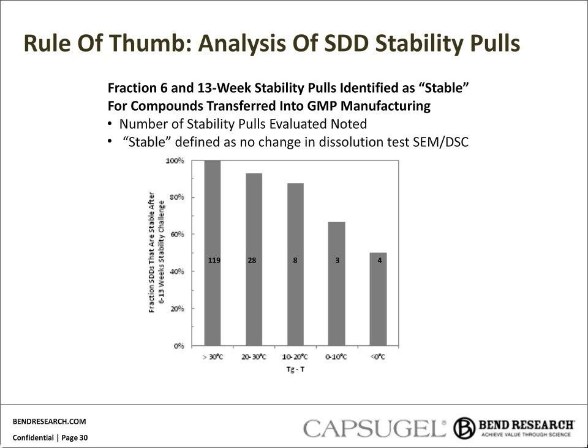And the other thing you'll note on this histogram are the numbers in each of the bar plots. And those numbers are the number of compounds that are in each of those data sets. And so you can also see that we just generally don't formulate, we try very hard not to formulate, such that we're going to expect to have a TG 10 to 20 degrees above the storage condition. So this is a really simple way of, with a small amount of material, coming in and saying, yep, physical stability looks like it's going to be straightforward, or we may want to consider packaging.